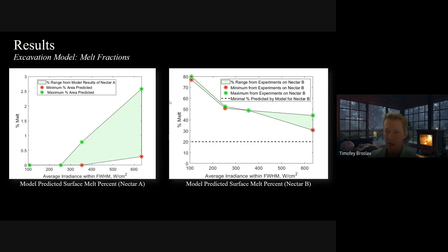For Nectar B, it predicted a minimum of 20%. This is because there was a stop condition in the model that basically stopped it running once melt exceeded 20%, based on a literature review of how melt affects stresses in rocks. Around 20%, you'd see a significant reduction in thermal stresses, and so this was used. So it's basically a minimum baseline, because I did measure the melt areas for Nectar B, and all of them are above 20% at least. So this definitely correlates well with what was observed.